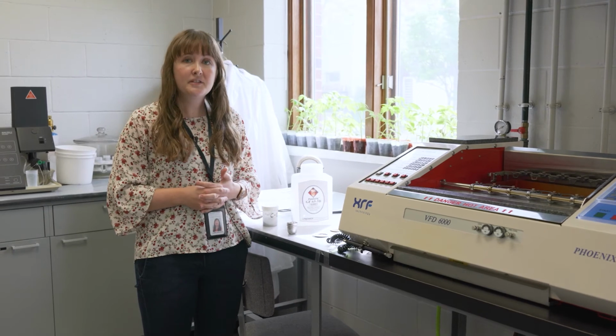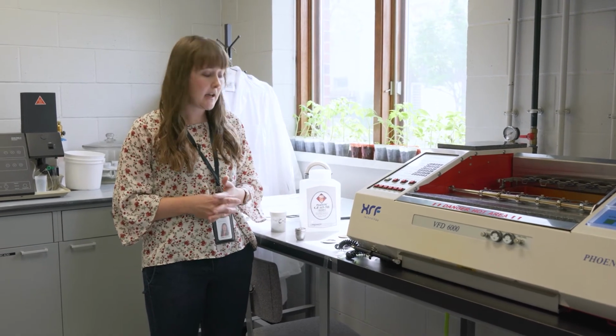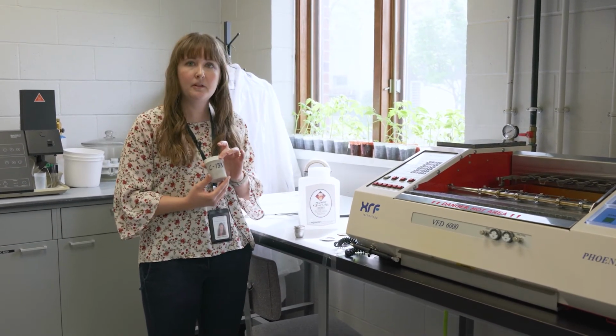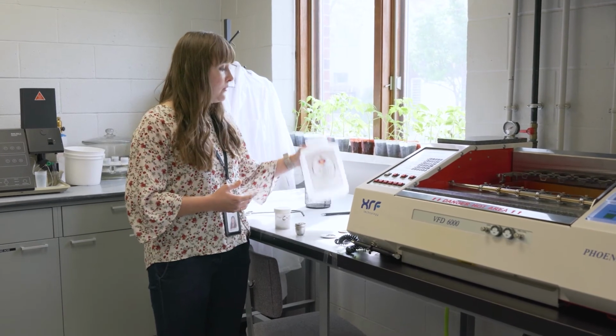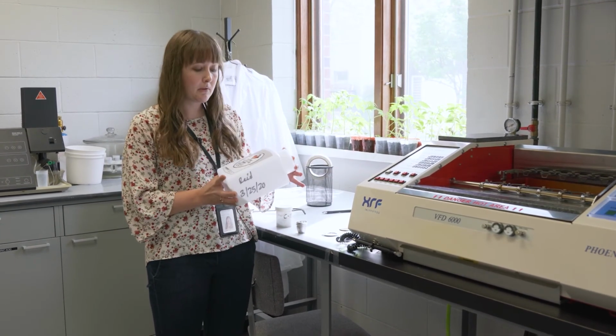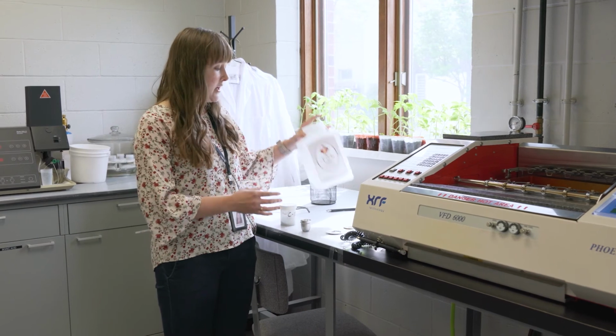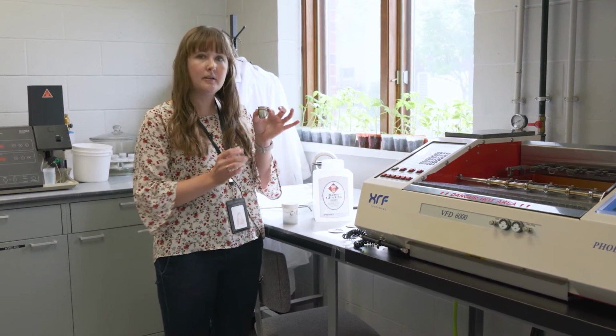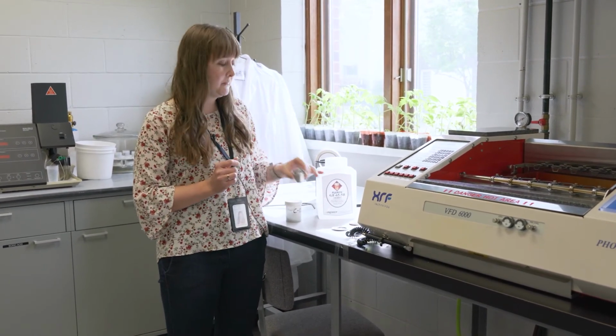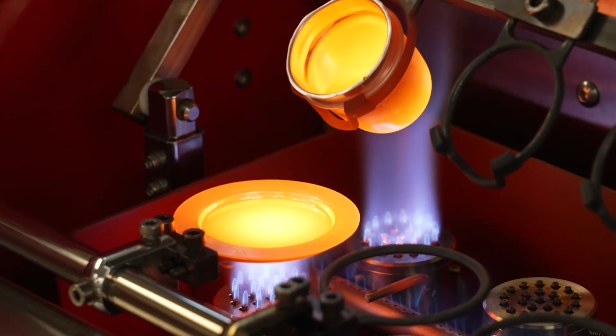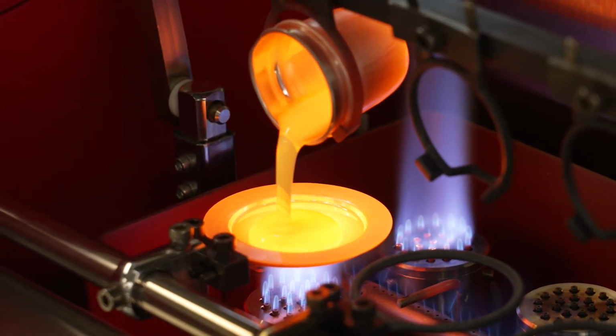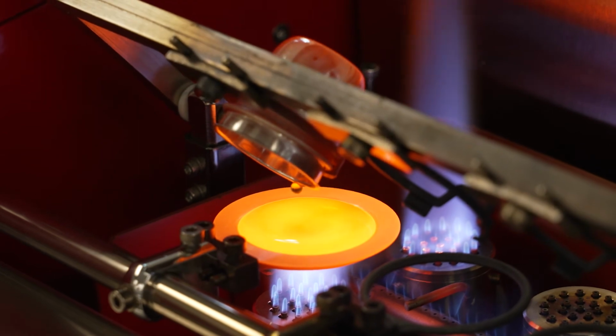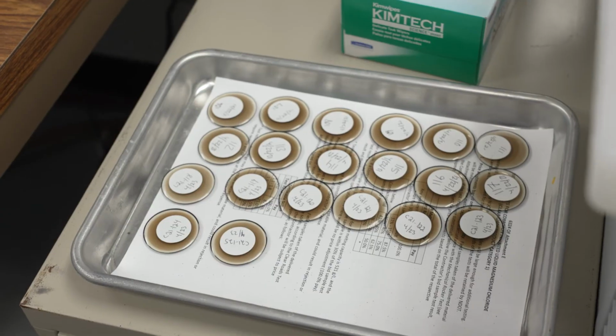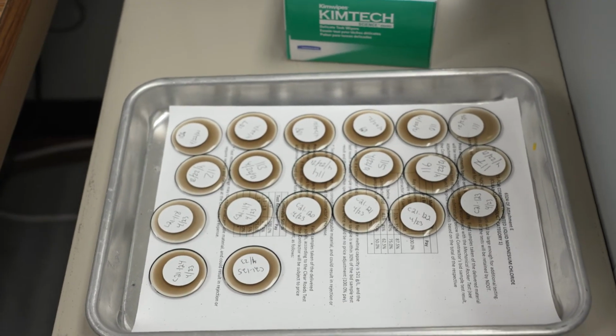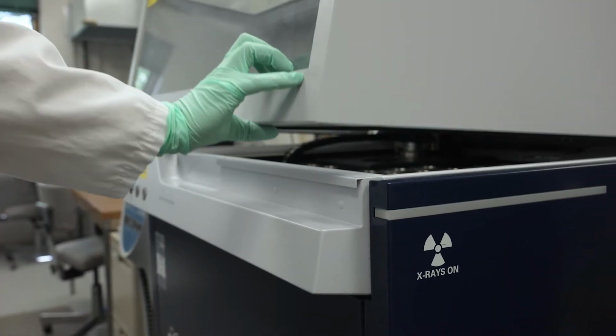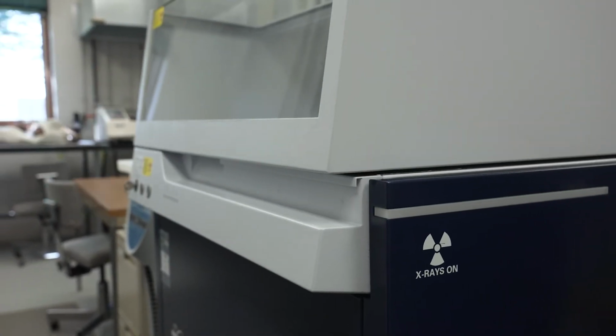For cement, we have composition requirements, and in order to test that, we take 1 gram of the cement sample, we mix it with 10 grams of this chemical, it's called flux, and we put it in another crucible, this is a platinum and gold crucible, and we use this machine to melt it down into a mold, and it pops out as a glass disc. And that glass disc then goes into our X-ray fluorescence spectrometer that gives us the results.